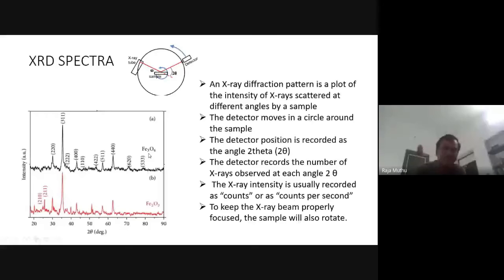If you take a sample and you get an XRD spectra which exactly matches with these peaks, then you can understand that your sample has Fe2O3 or Fe3O4. Suppose you made a composite which includes Fe3O4 and Fe2O3. Then you have to make a sample and test it with XRD. And if your spectra has peaks as available in the picture, then you can easily say that the sample contains Fe2O3 and Fe3O4.